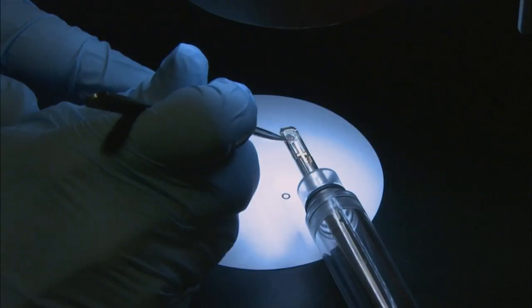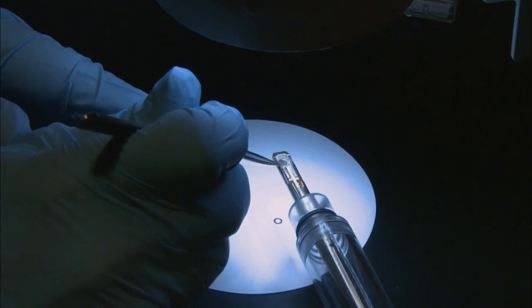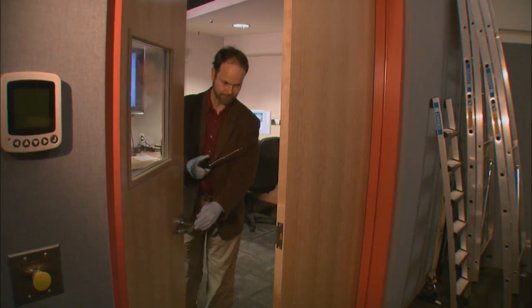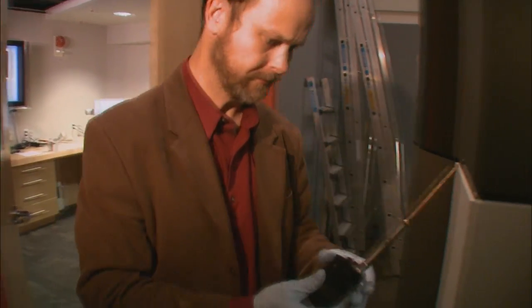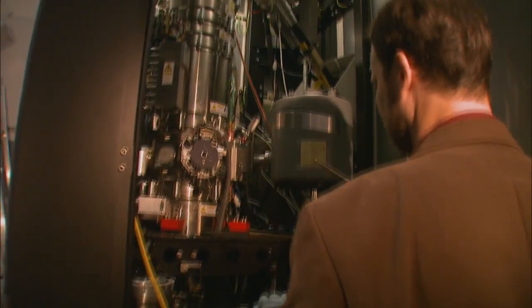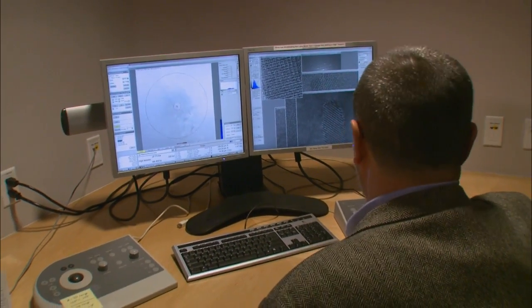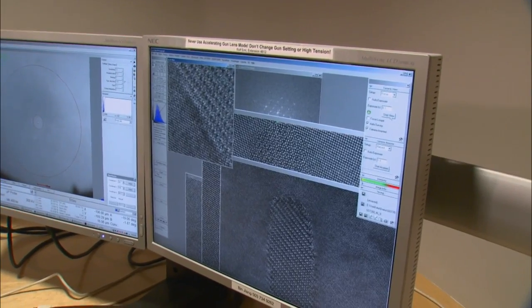It's very delicate. Figuring out the precipitate's precise atomic structure is essential in order to later test its strength. One of the most important things is to get a sample into the right orientation so that you're looking down a row of atoms and it can't be tilted. If the row of atoms is slightly tilted, then you wash out the resolution. The orientation looks good.